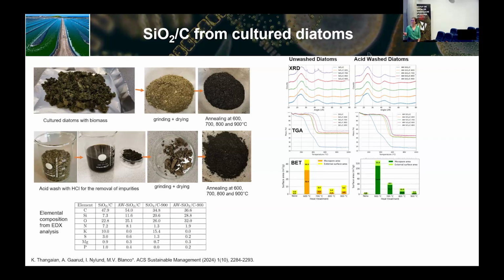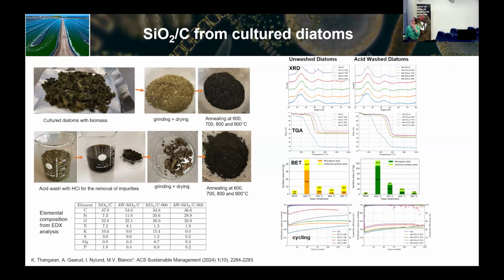We also did some BET measurements just to see the surface area. We can see there's a huge difference when you coat, when you do the washing procedure. And also we did the cycling. And we were very surprised to see that the non-washed materials behave much better than the washed ones, which means that the impurities are playing some role in the material. Might be that they are affecting conductivity, or it's not very clear for us, but we didn't expect to have better behavior of this. But still, the amount of carbon is too much.